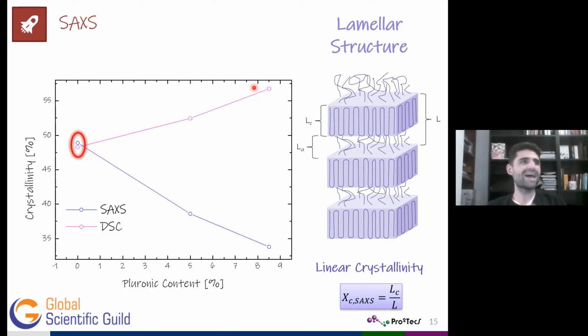However, when adding pluronic, a great reduction in the linear crystallinity can be seen in comparison with the DSC results, which takes into account the overall crystallinity of the system. And that may denote that there must be some crystals that have another kind of conformation different from the lamellar structure.